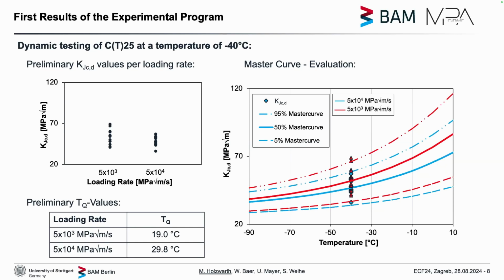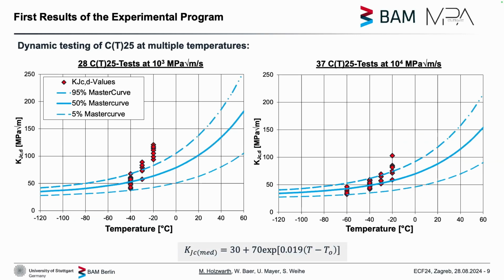And then we are done with our project, right? Well, we did just that. Reality isn't that nice. As we can see, the additional tests don't really fit into those tolerance bounds we just have evaluated via the standard. This means for at least this data set of CT25 specimens, the master curve is not applicable as is, but that's what we kind of expected from the start. We have to do some modifications to it to apply it to ductile cast iron.